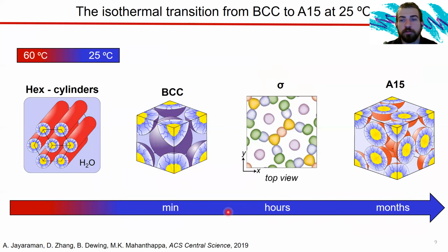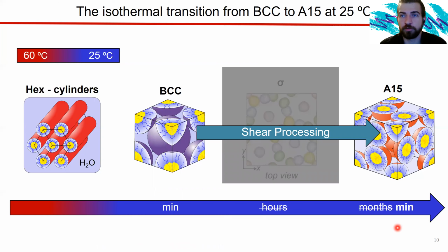Now, this is the thermal annealing procedure that the authors in that paper used. When you heat to 60 degrees C, you have cylindrical micelles, and as we begin to cool, we quench to 25C using liquid nitrogen boil off, so it's pretty quick. After a few minutes, you have a body-centered cubic phase. A few hours, you have this Frank-Caspar sigma phase come in. It's going to take you about 5 months until you have a complete Frank-Caspar A15 structure, and that's the equilibrium phase. Now, what I'm going to show you today is that using shear processing, we can shorten this time frame from months to minutes. And we're going to skip this Frank-Caspar sigma phase entirely in the process.